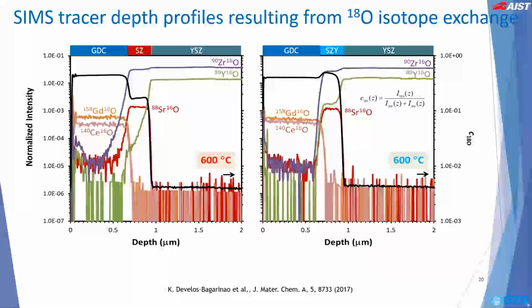This shows the SIMS depth profiles of the samples isotopically exchanged at 600 degrees Celsius for 5 minutes. The individual elements comprising each layer are shown as plateaus in the depth profile, and the boundaries or interfaces between layers can be seen as sharp drops in the profile. To illustrate this point, for the plot on the left, we can see the gadolinium and cerium signals as plateaus in the GDC region. And at the interface with the strontium zirconate layer, we can observe that these signals exhibit a drastic drop, simultaneous with an increase in the strontium and zirconium signals, indicating the onset of the strontium zirconate region.